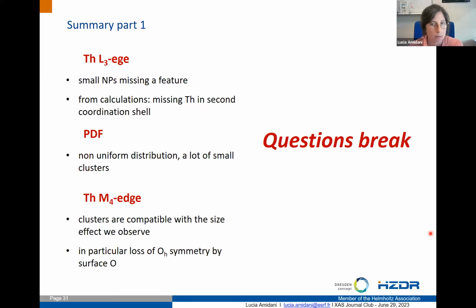I don't know if it's clear, but the reason I'm not doing this is that it is really hard to find realistic models of small nanoparticles of actinides. Up to now, I don't think there are many theoreticians that can give me a structure of such a relaxed nanoparticle. The cluster is different, because in the cluster I have a real measured structure. This was key to simulate the M edges.